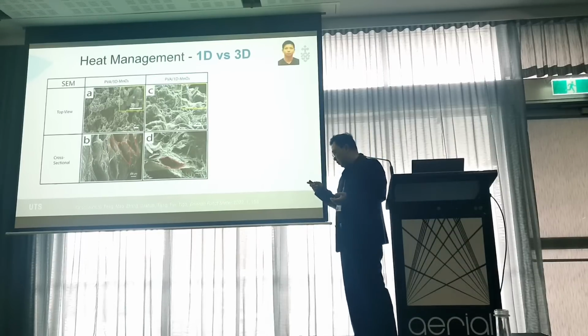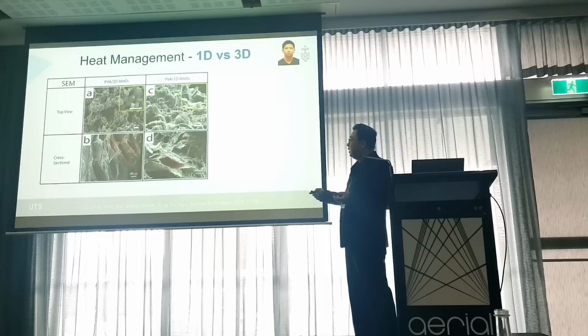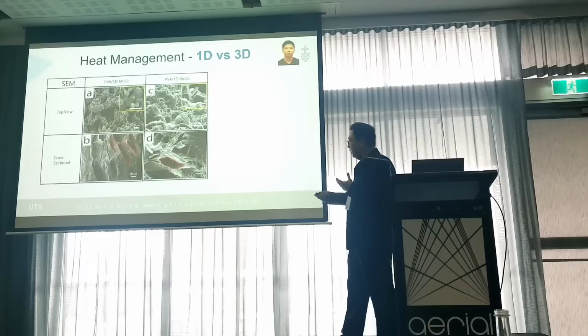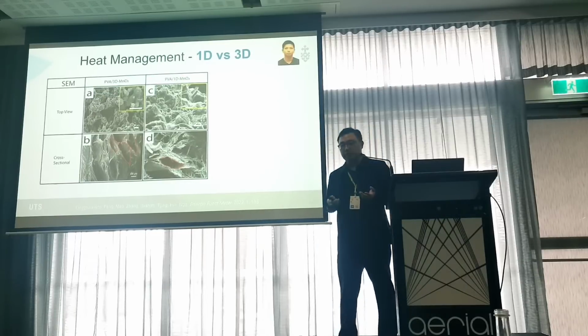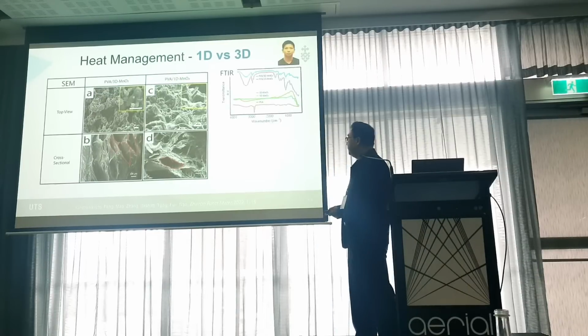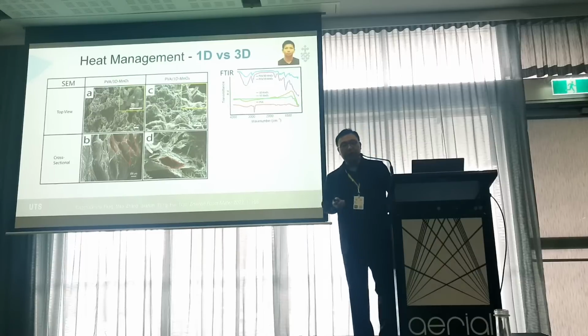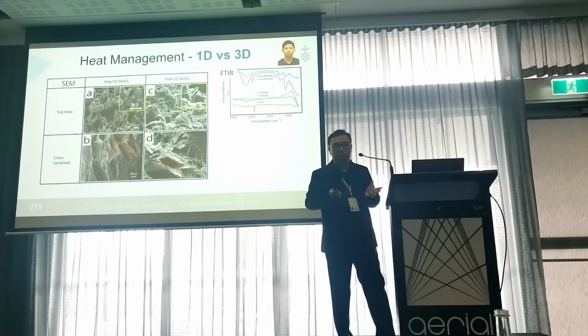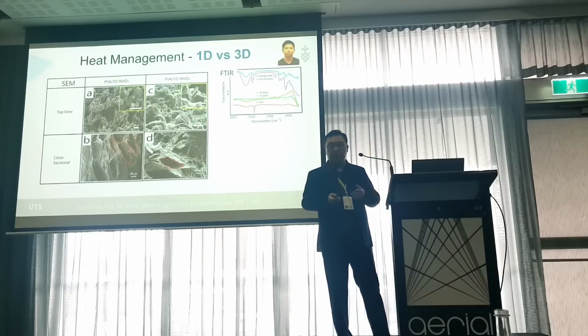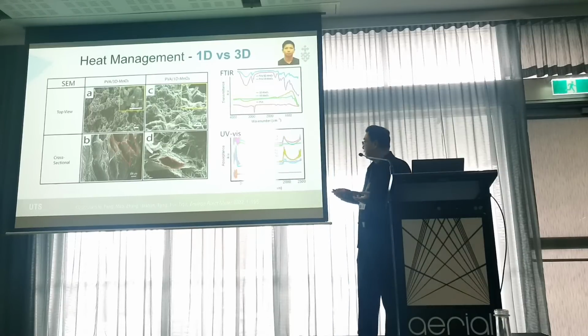Through the SEM images, we find that the 3D nanoparticles or 1D nanorods were embedded in the hydrogel matrix clearly. And both hydrogels have this microporous structure. This structure will facilitate water transport within the hydrogel. We also characterize them by FTIR, and as you can see, all the characteristic peaks were observed, as well as using the UV-vis.